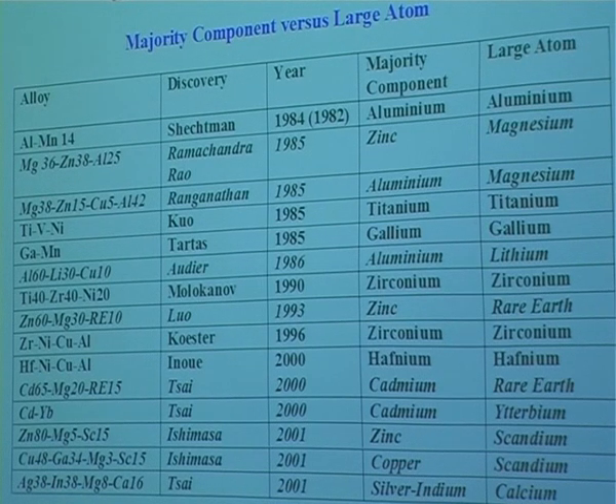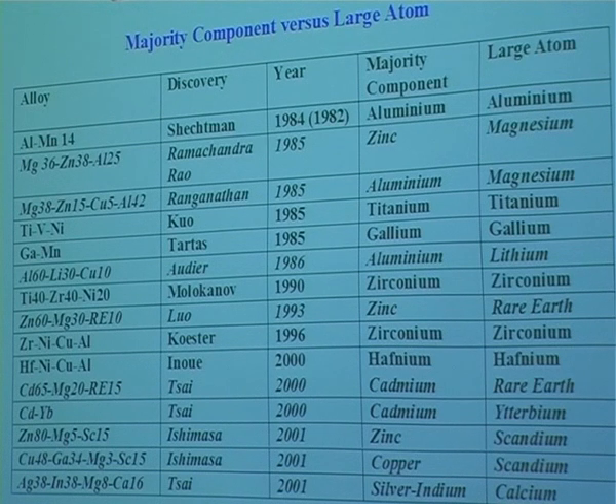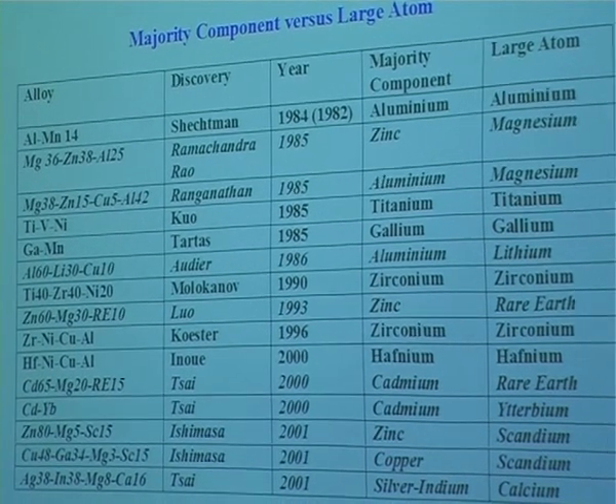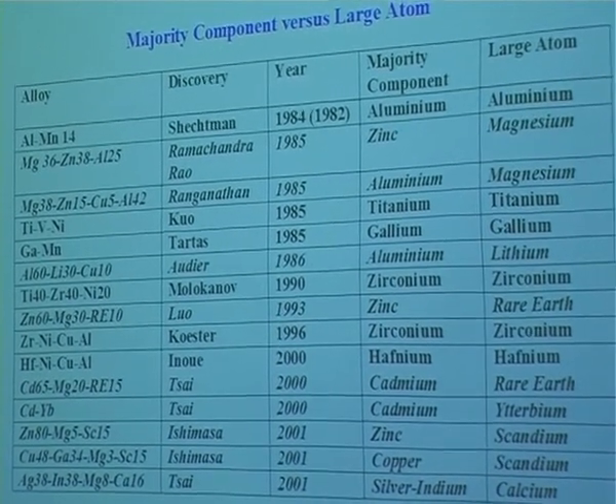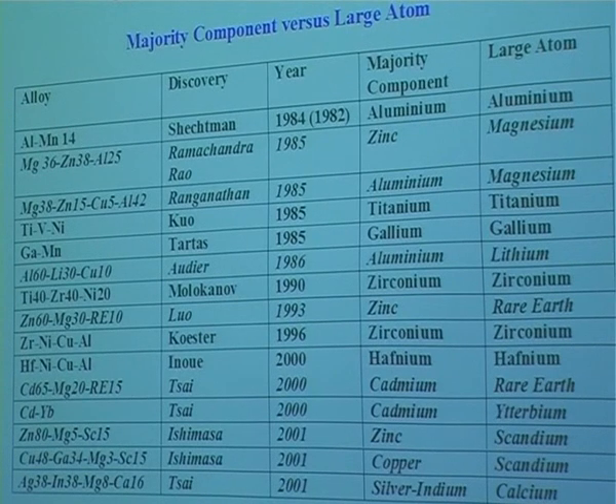Then I already referred to the titanium vanadium nickel by Kuo in 1985, and by Audier in 1986 of aluminum lithium copper, and Luo in the zinc magnesium rare earth, and then of course Professor Inouye in the hafnium alloy, Tsai's work I already referred to, and similarly Ishimasa found a number of quasicrystals. So if you look at the many systems, very many systems, especially in that period where I have given from 1984 to almost 2001, many of them were found by Asian scientists working on this. It's quite an interesting thing.